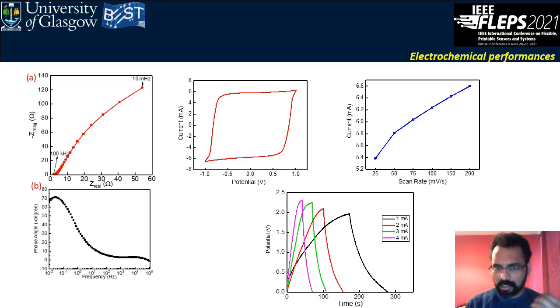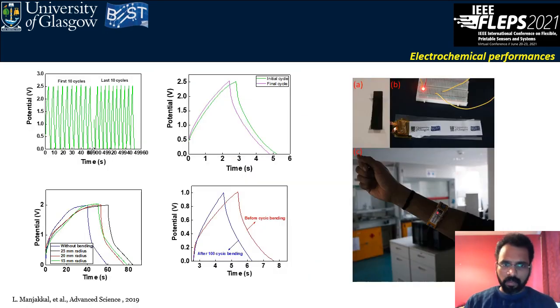And further we characterized the galvanostatic charging discharging analysis for different applied currents. You can see here that with increasing current there is a saturation potential. We measured the saturation potential of the device for different current densities. In previous work, we also reported the long charging discharging. You can see here that for 10,000 cycles we characterized the charging discharging of a device, the first 10 cycles and the last 10 cycles. And here you can see the initial cycle and the final cycle have almost similar properties. That means that this supercapacitor shows very good performance even after 10,000 charging discharging cycles, even at 1 milliampere current.